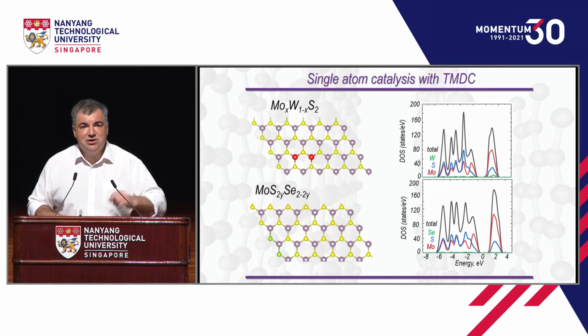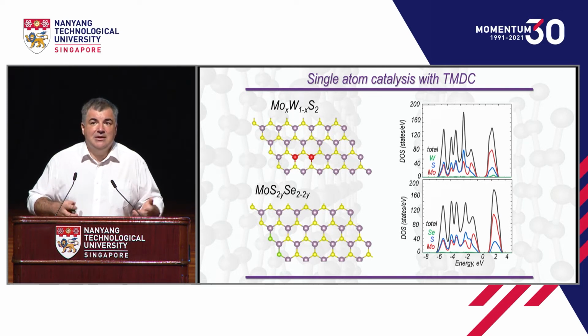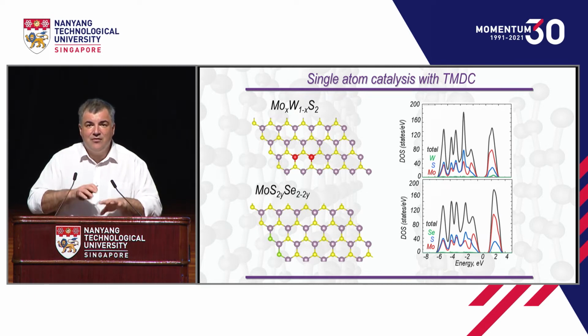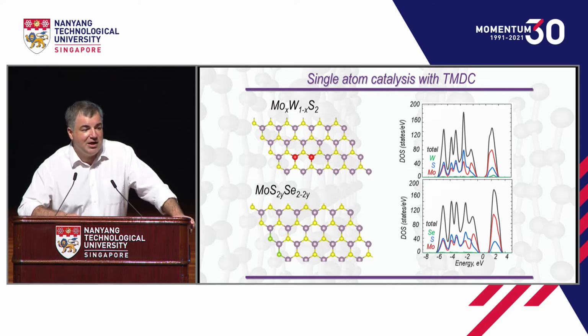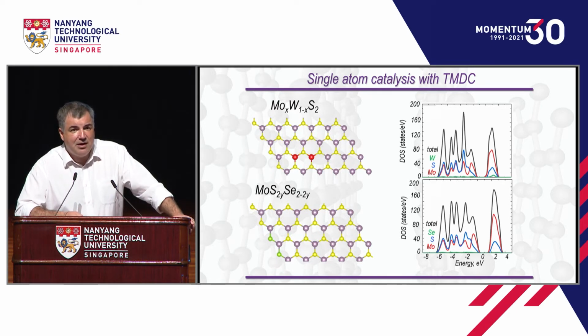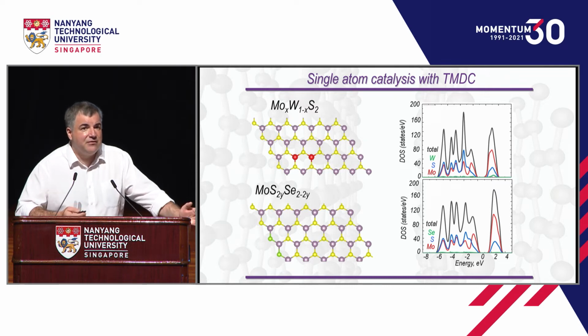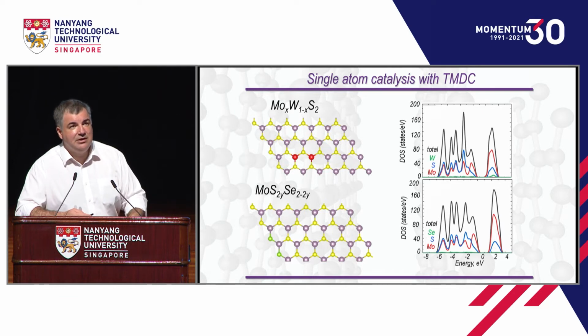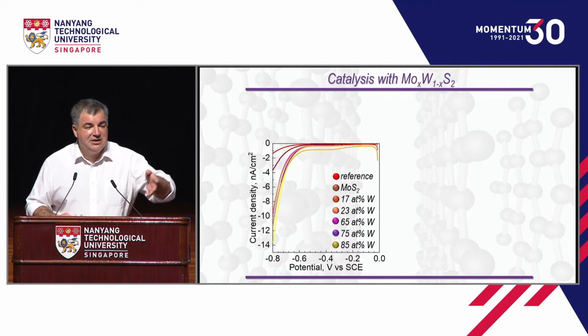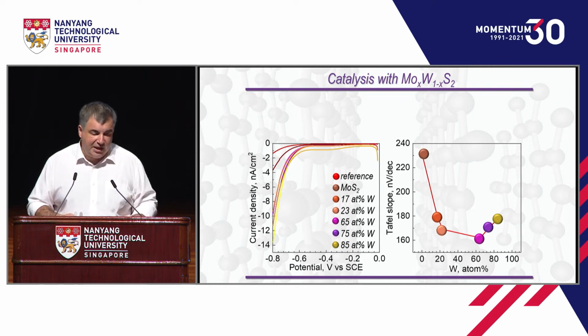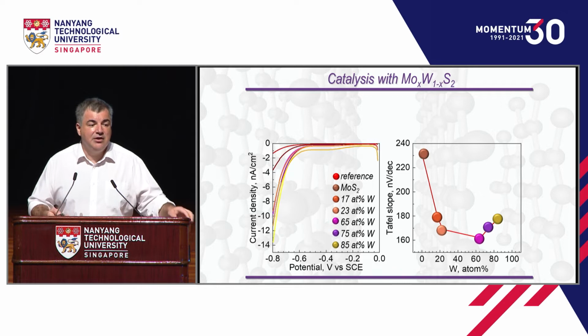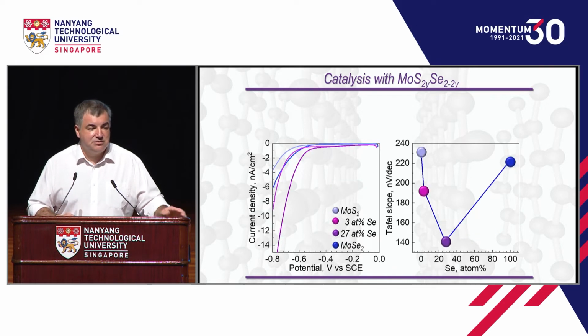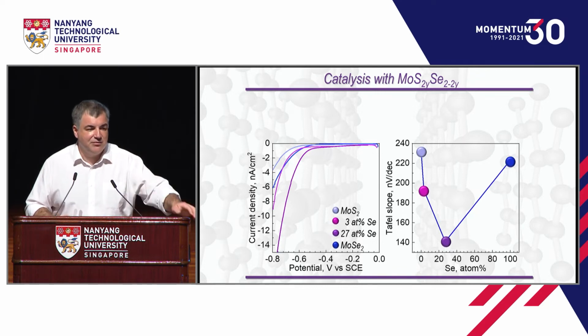And for example, for this case which I showed you, the emission of light, you really need to guess what kind of alloy do I need to put together to get to a particular wavelength. So in our case, we create a huge database of different alloys and different added atoms in our crystals, and we use machine learning to predict their properties. So in this case, for example, we try to use those alloys for catalytic properties, and we try to recreate the volcano plot, where we can replace molybdenum with tungsten or sulfur with selenium.